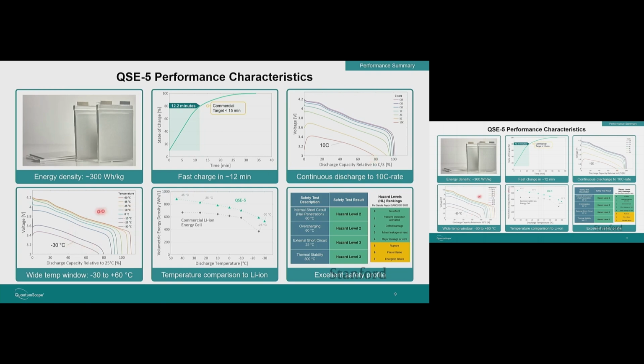This shows the temperature range from 60 degrees C down to minus 30 degrees C. It will operate across the full temperature range. That's traditionally been a real challenge for solid-state batteries, which often need to be heated to work. So this can work at room temperature and below, all the way down to minus 30. And by the way, in a way that is better than most lithium-ion batteries that you'll find on the market at low temperature as well. This, in fact, shows that comparison of a lithium-ion cell that's popular in electric vehicles today versus ours, showing the energy density versus temperature, where our battery is higher than a lithium-ion battery across temperature.